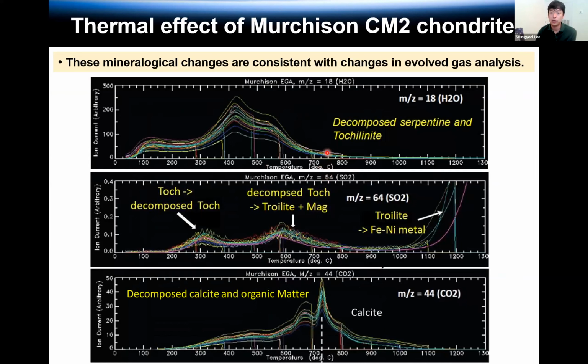Yeah, I also checked the evolved gas analysis at different temperatures, with increasing temperature. So this image is from the H2O emission gas during the heating. So this water emission led to the decomposition of the serpentine and tochilinite phases, and then the olivine and troilite recrystallized.